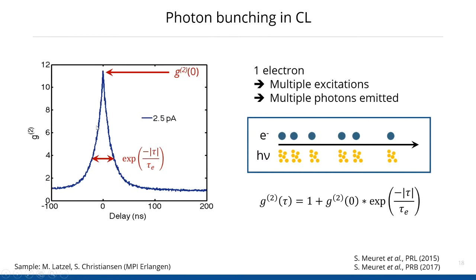You can measure the lifetime without resorting to a pulsed electron source. This really relies on the fact that the electron has enough energy to excite more than one photon in a material in a short period of time. This is something you don't see in optics normally, because a laser can only excite one photon for one incoming photon, so the bunching effect will not be visible. This is really something unique to electron microscopy and it is very useful.